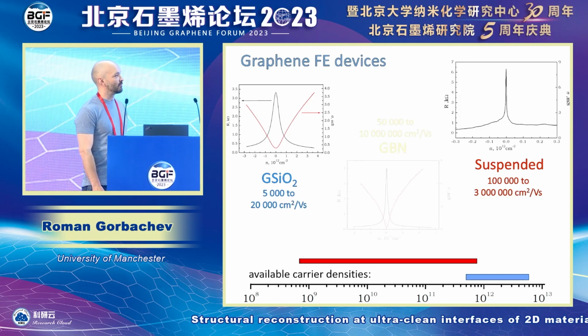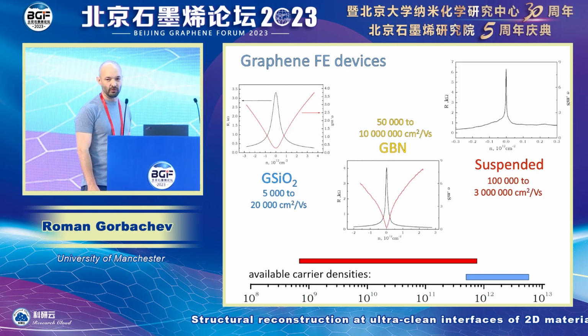And then a few years later yet, Columbia University managed to produce graphene on boron nitride. And that was a critical step where we put graphene on an atomically flat and clean substrate. We see dramatic improvement in terms of the mobility of the devices. So currently at low temperatures, we hold the record of 10 million, but I'm sure it can be improved in the near future.